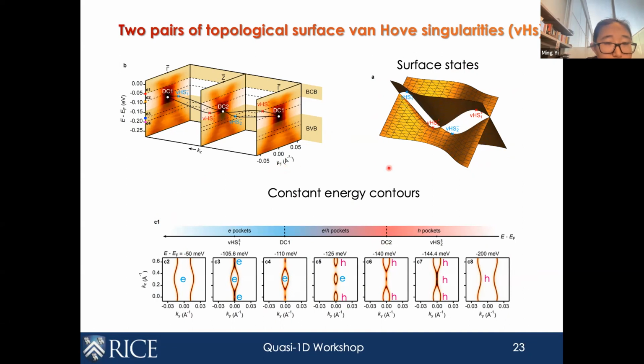So let me try to walk you through this. Given this kind of structure, let me first start close to the Fermi level, from high on top. So if we're at this energy, we will have this kind of Fermi surface, which has a large open Fermi surface with almost quasi-1D dispersions, which is the electron-like. If we go down in energy, the first Lifshitz transition occurs at the energy of the top pair of Van Hove singularities, and this is where this large pocket gets pinched into three electron pockets. And then if we go further, the next interesting energy is the top Dirac point at the gamma point, and this is when the pair of electron pockets here change into hole character.